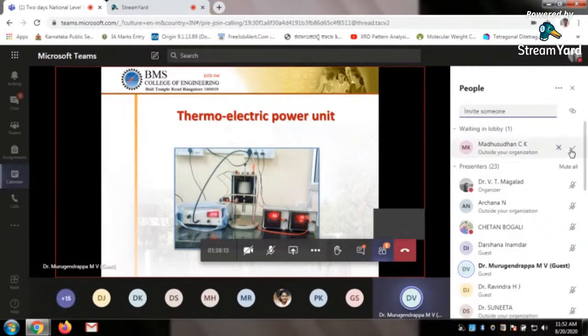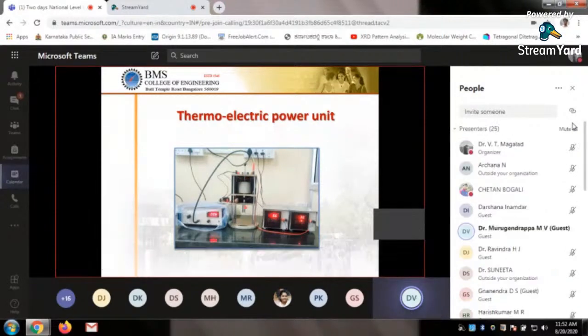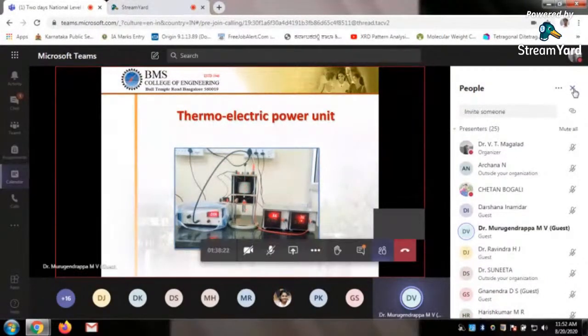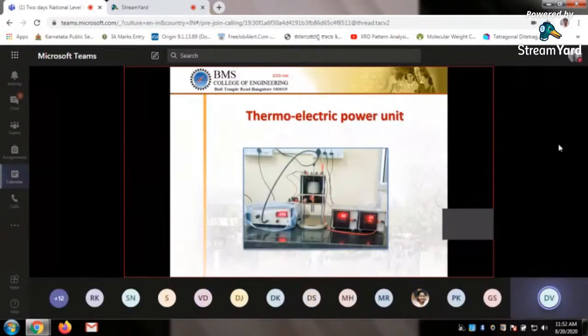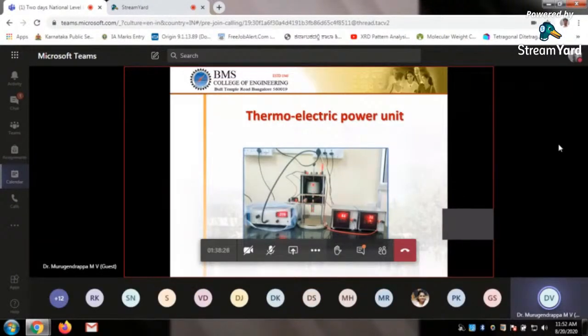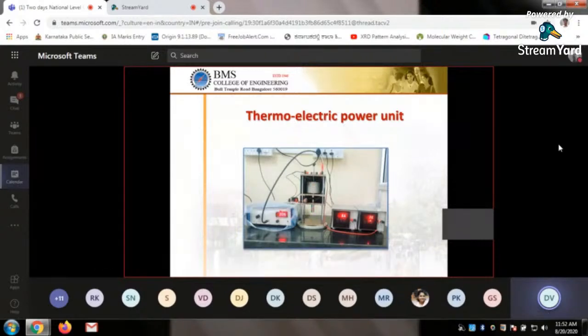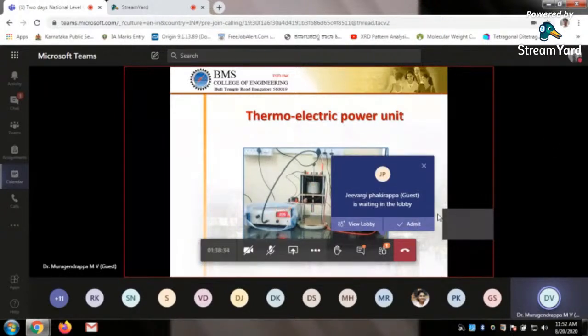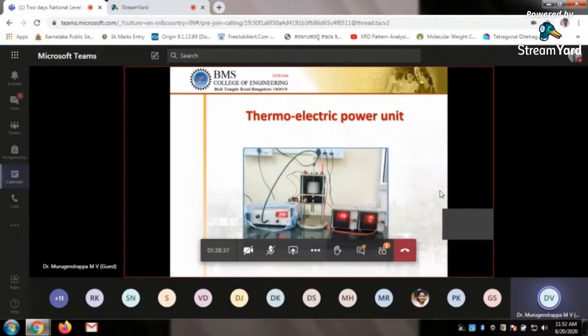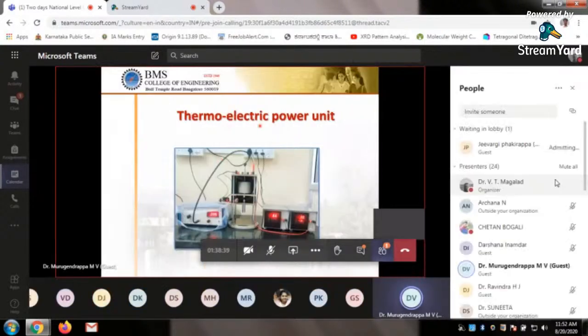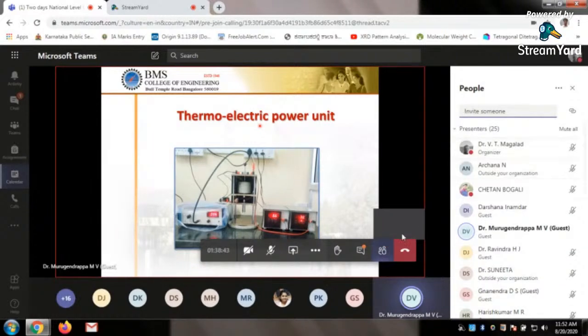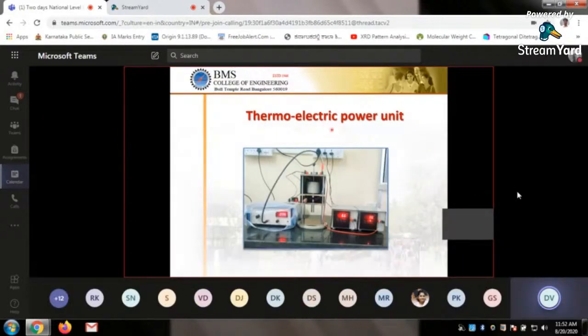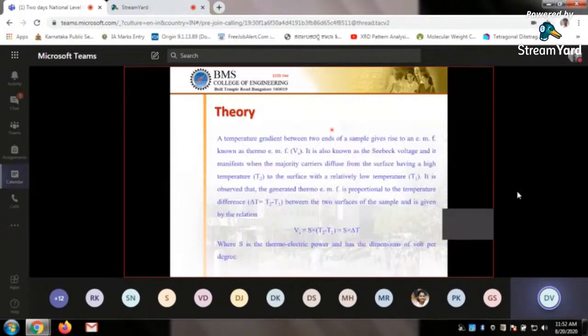The lower one gives you 36 and the upper one gives you 66, and you can go up to 200 degrees, whatever. By variation in the temperature, the lower surface is at low temperature and the upper surface is at higher temperature. Because of the temperature difference, it produces an EMF that is called thermo EMF. So if you connect a nanovoltmeter, it gives you better values, and it depends on the material. Most people are working with thermoelectric materials, because nowadays heat is simply being wasted. Why can't we convert that heat energy into electrical energy? People are working on this. This is one of the very good areas where, if you're interested, you can work. And what we're actually doing, we know delta T.